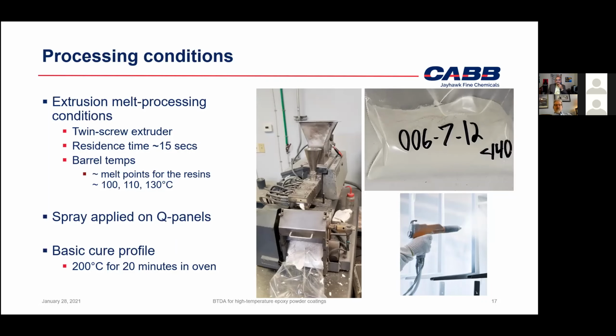The barrel temperature we varied depending on the melt viscosity of the primary resin. So the 2.5 type we looked at essentially 100 degrees C. The 4 type, we bumped it up about 10 more degrees. And then the 7 type was extruded at 130 degrees C. The whole point there is just to have the right kind of viscosity going through this compounding step. So the material was fed, like I mentioned, with the RPM set at 500.